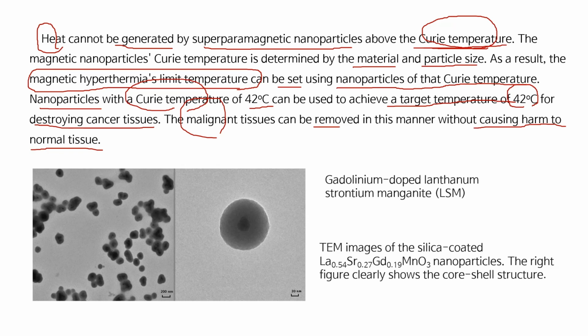For this purpose, we synthesized gadolinium doped lanthanum strontium manganite. So this is the chemical formula. This figure shows TEM images of the silica coated gadolinium doped lanthanum strontium manganite nanoparticles. The right figure clearly shows the core shell structure. So these LSM particles are completely encapsulated by the silica.